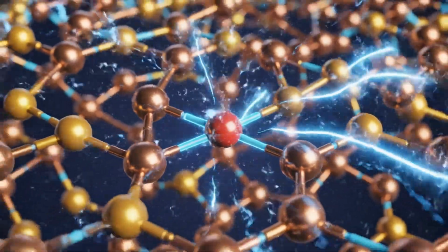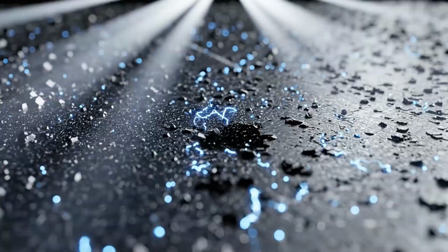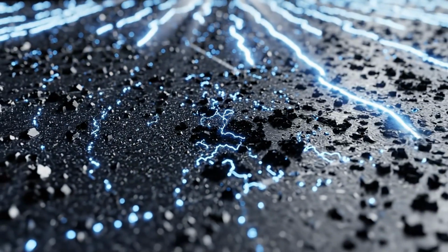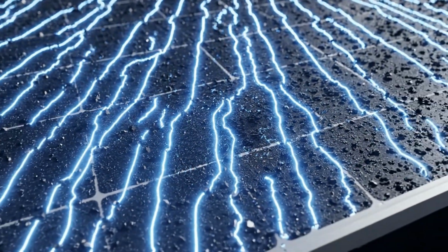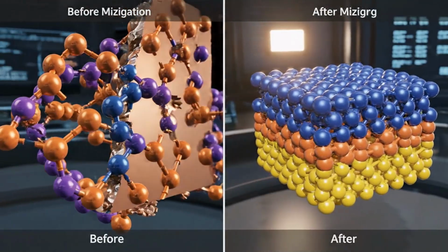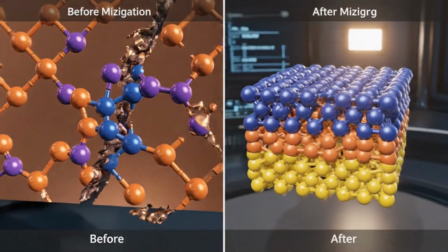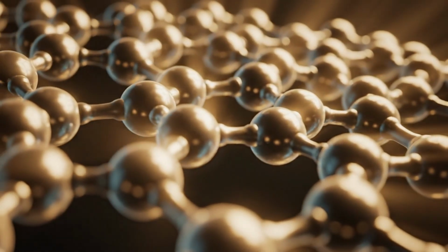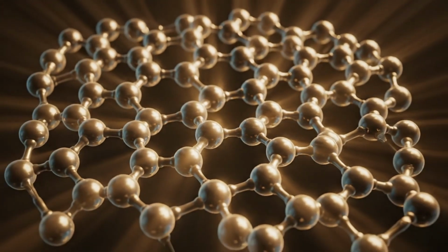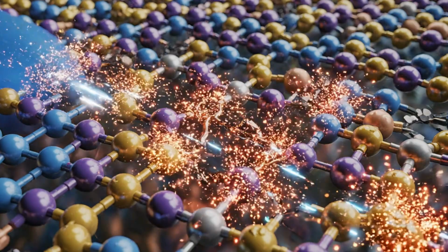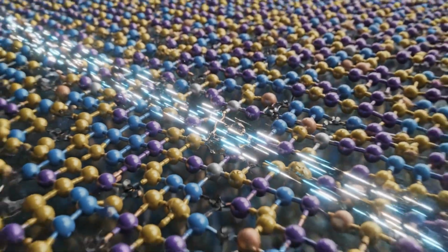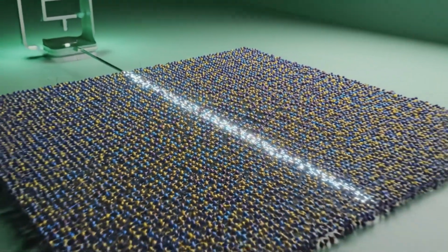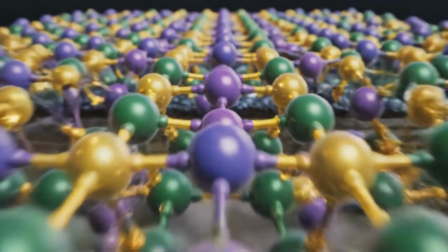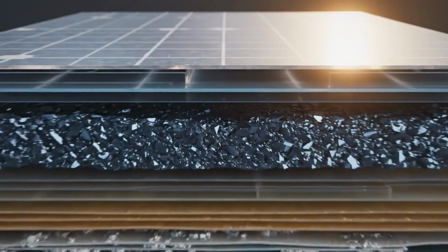In fact, many of the most important solar technologies went through similar phases. Silicon itself took decades to climb from single-digit efficiencies to today's mature designs. The question is whether kesterite's barriers are fundamental, or simply engineering challenges, repairing the crystal instead of replacing it. What makes recent kesterite research interesting is that scientists are no longer trying to reinvent the material. They're trying to heal it. One approach involves post-processing treatments, essentially repairing defects after the crystal has already formed. For example, thermal treatments in hydrogen-rich environments have been shown to dramatically reduce defect density.